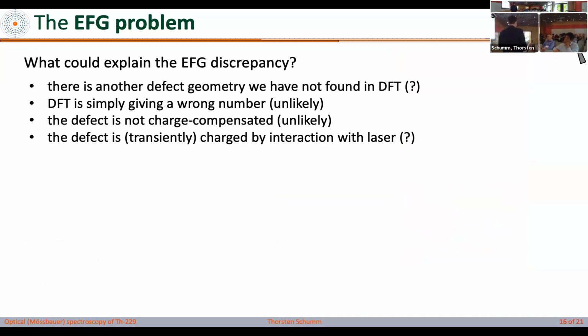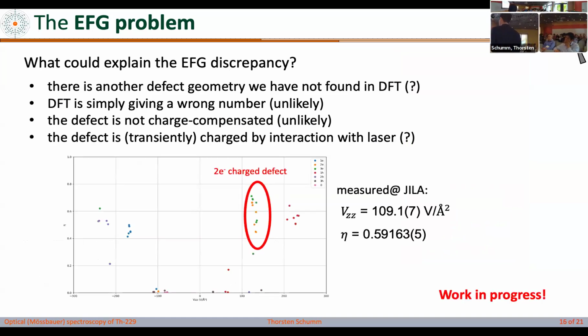And there's one thing that could maybe resolve this, and that is that this defect is not electronically neutral at the moment when we interrogate it. It could be that there is electronic charge sitting on the defect, maybe because the laser is pumping electrons into the conduction band and they trap at the defects, which is known to happen. So if this defect was intermediately charged, then that would actually fit really nicely. But that's something we have to study, and how we will do that, I'll tell you in a few minutes.